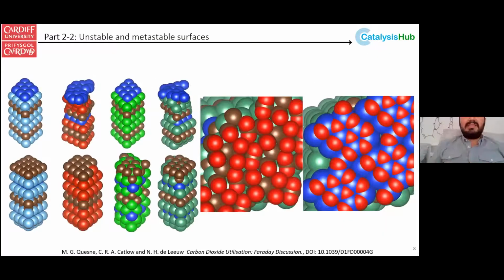So the first thing that we did was we looked at the stability of the different surface terminations. As you can imagine, with these slabs, there are only 2 possible slabs that you can get. One that has metal on the one surface and silicon on the other, or metal and carbon slabs. So you can either cut between the metal and the carbon or between the metal and the silicon. And then obviously you decide which half of the slab you relax.